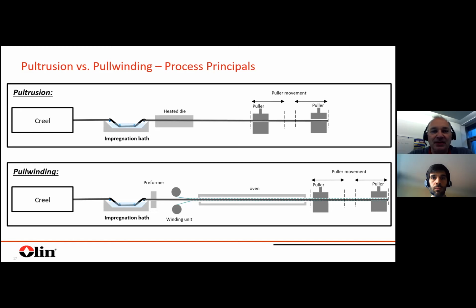So just as a scenario, I will not go too deep because I think pultrusion is well known. You pull your fiber through an impregnation unit, often a bath. You have a heated die where you cure it, and then you can wind it or cut the parts. In pull winding, you have the same up to the impregnation bath. Then you have a kind of preforming unit where you just form your profile. Afterwards, you have a winding station to consolidate this profile, and you have a post-curing oven. So really, as described before, the cure scenarios are quite different.